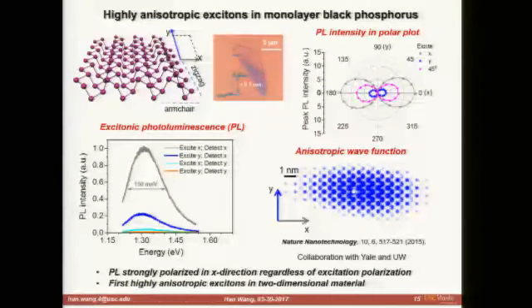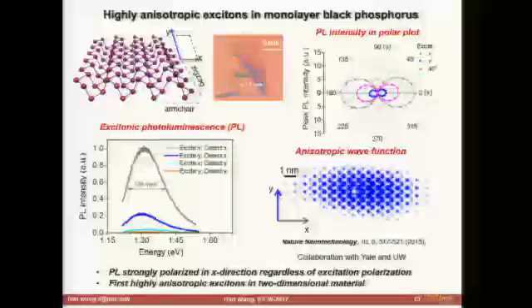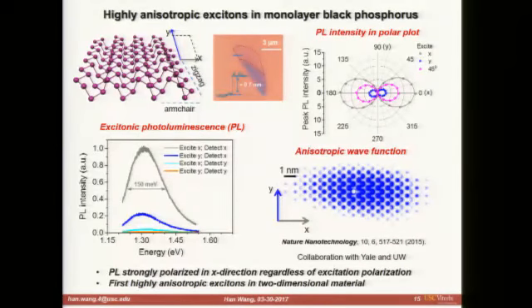The most interesting thing we see is that in our photoluminescence measurement, no matter how we polarize the incident laser, the emitted light, the PL, is always strongly polarized along the x direction of the crystal, with almost nothing coming out along the y direction. This reminds us of the optical property of one-dimensional materials like carbon nanotubes. But essentially what we have is a quasi one-dimensional material where the physical geometry still looks 2D, but the optical property resembles that of one-dimensional materials.